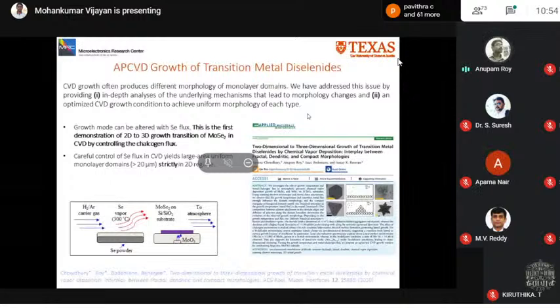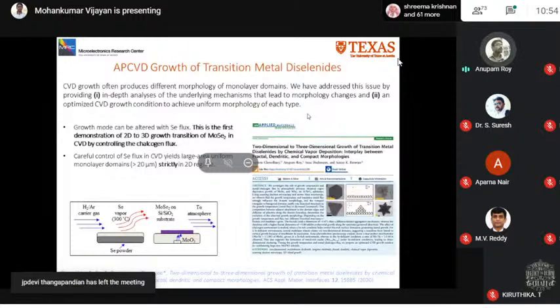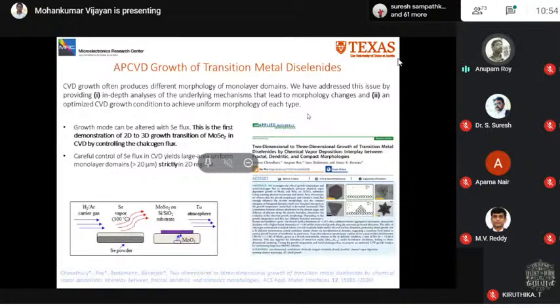I'll keep the presentation very short, and I'll focus mostly on our recent work where we studied the growth more systematically. So it is observed that CVD growth often produces different morphologies. So in this work, we provided an in-depth analysis of the underlying growth mechanism corresponding to different morphologies and an optimized condition to achieve uniform morphologies of each type. We observed that the change in growth mode from 2-dimensional to 3-dimensional can be altered with selenium flux.